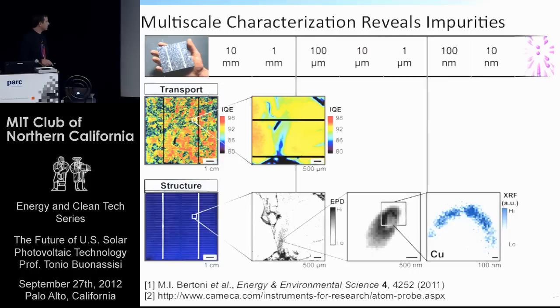And as you zoom into an individual dislocation, you can see metals surrounding that dislocation core, Cottrell clouds, if you will. And this is a synchrotron-based nano X-ray fluorescence tool that has a spot size of around 40 nanometers, which is around 1,000 times thinner than the diameter of your hair. And it is truly fascinating to think about that tiny, tiny spot rastering over the sample in a controlled fashion such that one line matches up to the next. That's truly a feat of engineering.